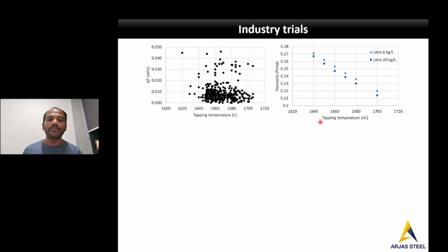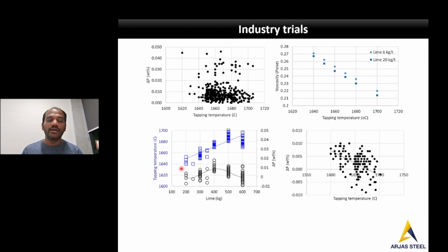You can see the phosphorus reversion is one of the indices for the slag carryover, which is very random before adopting our change in practice. And the change in practice, what we did, is addition of lime towards slag engineering with respect to the tapping temperature. If the tapping temperature increases, the amount of lime added also increases, and addition of lime basically decreases the viscosity of the slag.